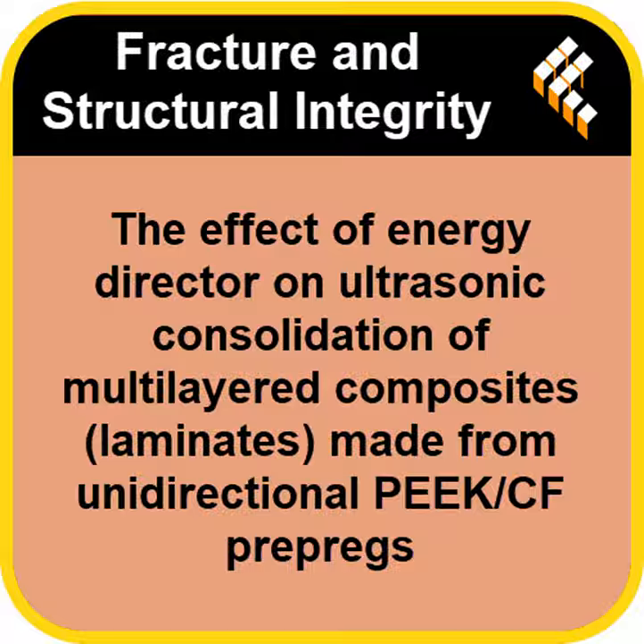A cleaner, shorter, and stronger approach. 800 milliseconds without the conventional energy director gave them an ILSS over 50 MPa. And we saw that the strength of that bond really hinges on that extremely fast transition from slow surface friction heating to that deep, intense viscoelastic heating. Right, that 800 millisecond sweet spot is all about balancing the speed you need against the damage you cause by overheating in that intense phase.